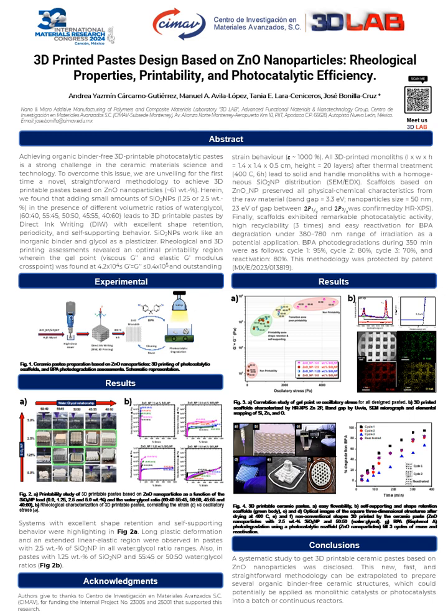in the presence of different volumetric proportions of water and glycol leads to 3D printable pastes by the technique of direct ink writing, showing an excellent retention of shape, periodicity, and self-supporting behavior. Silicon oxide nanoparticles work like an inorganic binder, and glycol as a plasticizer. Rheological and 3D printing assessments revealed the optimal printability region, wherein the gel point lies.